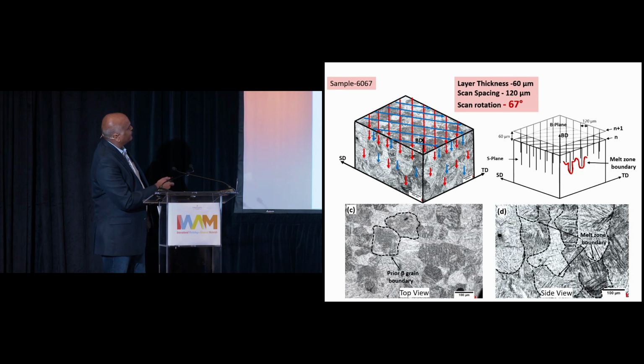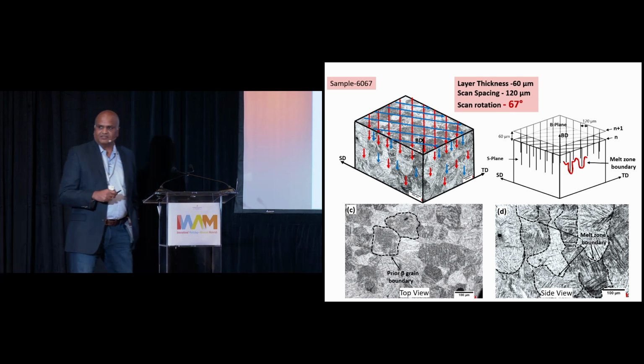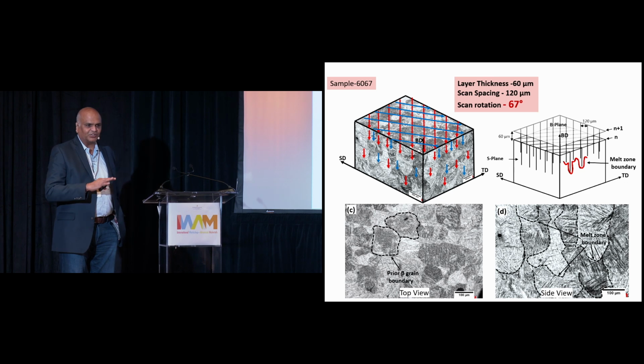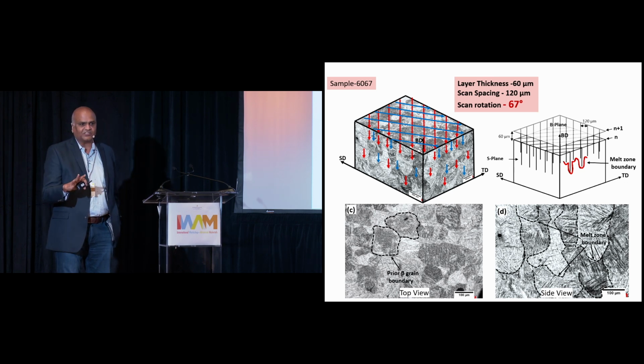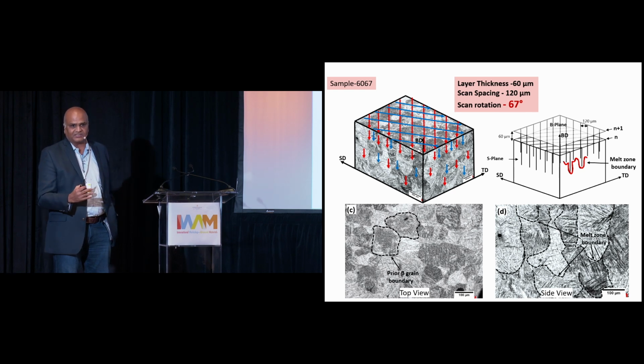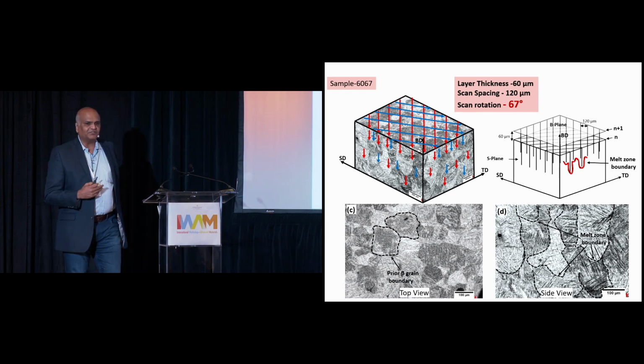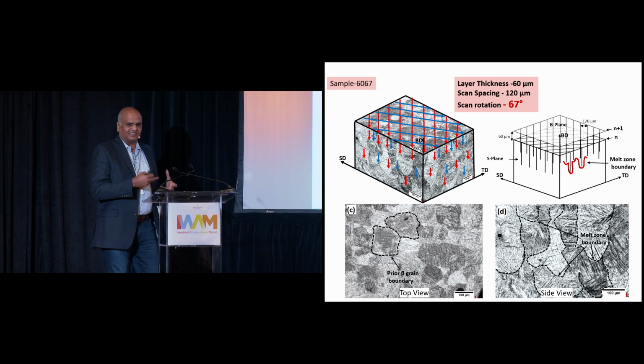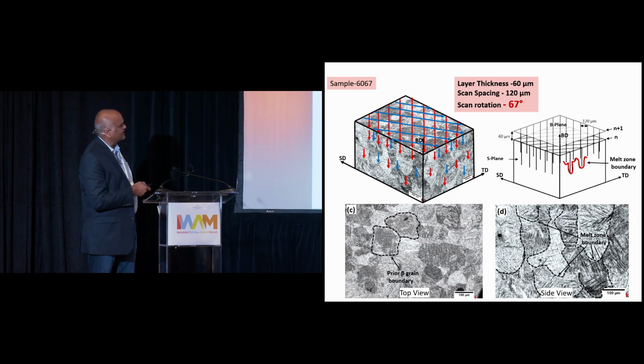If you increase the layer thickness to 60 microns and do the scan rotation at 67 degrees, you're able to break both the square grains and the columnar grains. So the alloy composition is the same—we didn't change it. We can also change the composition and do these things, but just by playing around with the print strategies and process parameters, you can get the meso-structure that you want.